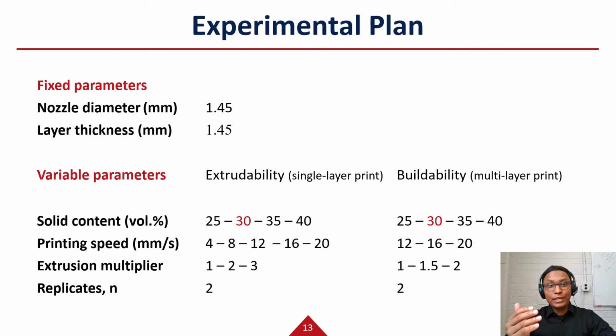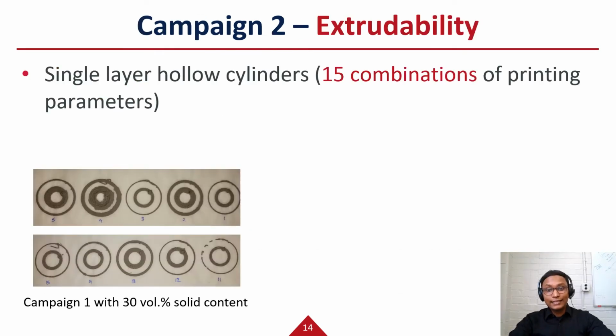Considering the workable range identified in campaign 1, we experimented with 4 different solid contents. For each one of them, we experimented with a wide range of printing parameters. We also conducted some initial experiments by printing single tracks to narrow down the range of parameters before the second campaign. In this campaign, we printed single layers of a hollow cylinder with 15 different combinations of printing parameters. We had 2 replications to ensure that the result is consistent.